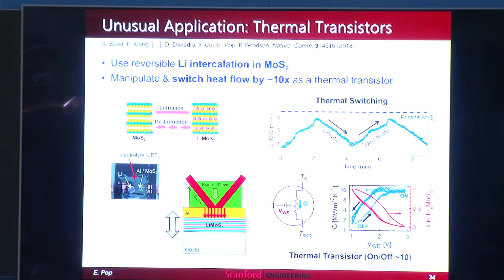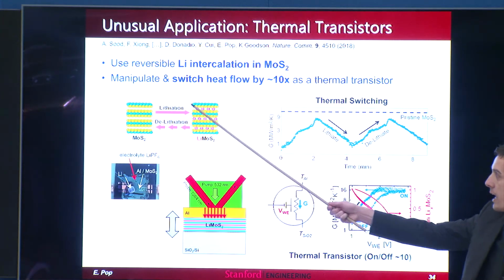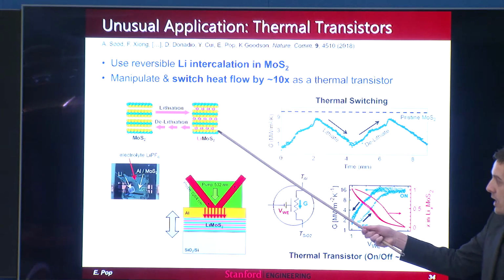Another unusual application is this concept of thermal transistors. The concept of actively controlling the flow of heat has been around for a while. But it turns out it's quite difficult, right? You can control electrons very nicely because they're fermions. You have a gate, you can whip around the Fermi level. But phonons are bosons, and you can't move around their Fermi level because there's no Fermi level, right? And so the way to do this, in this particular case, is to work with multi-layer MoS2 and to push lithium atoms between the layers and then to pull them out.